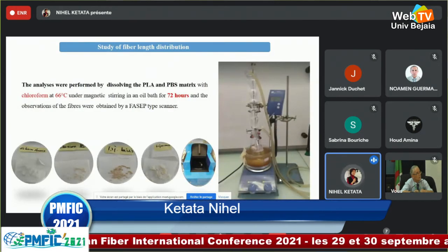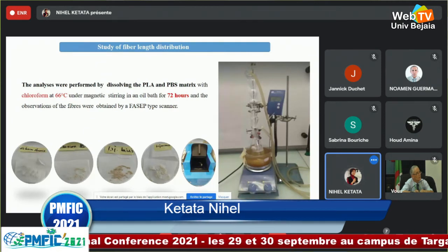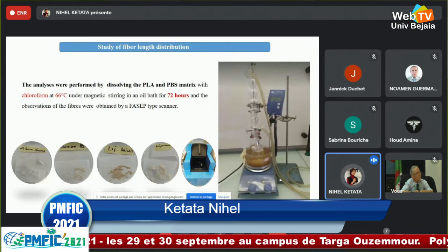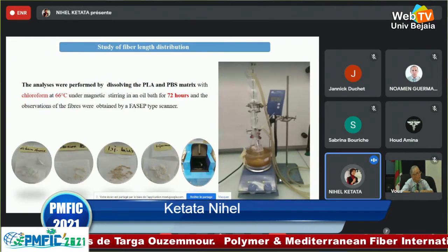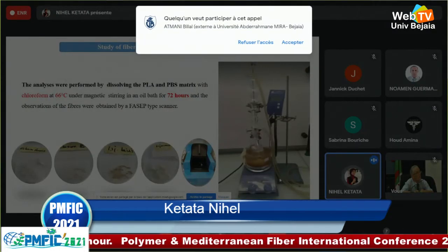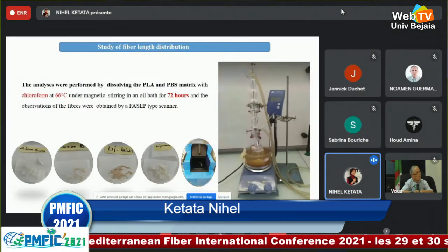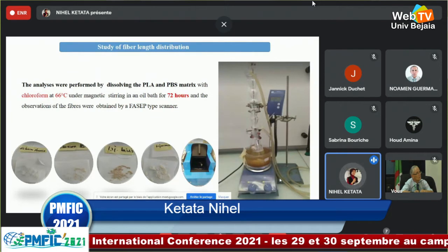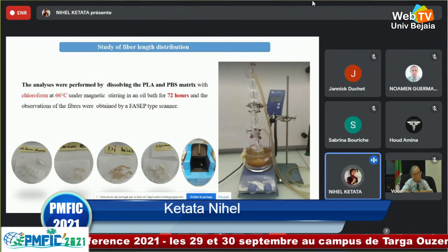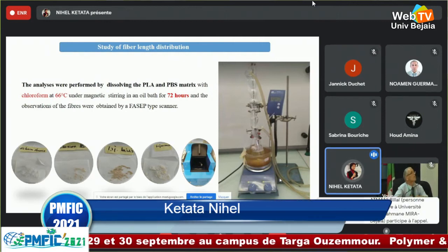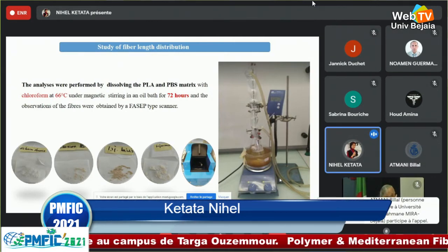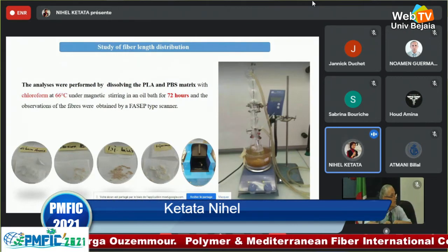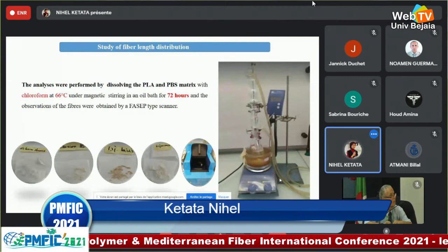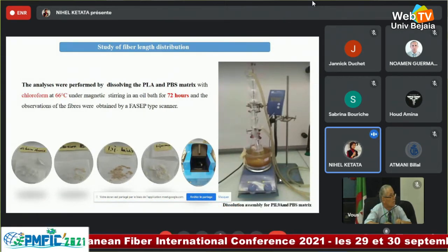Moving now to the study of the fiber length distribution. In the following, we present the analysis of the fiber size distribution after a comparison of the flax fiber in the matrix by twin-screw extrusion and single-screw extrusion, and after injection of the material, presented at the beginning of the section. The analyses were performed by dissolving the matrix in chloroform at 66 degrees under magnetic stirrer in an oil bath for 72 hours. The observation of the fibers was obtained by a scanner.